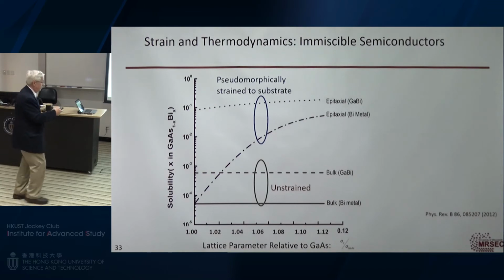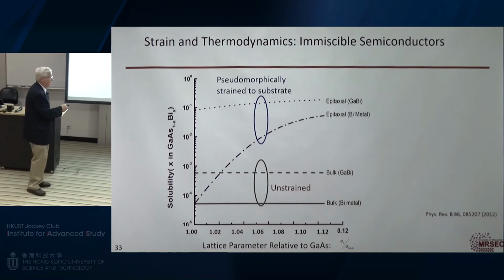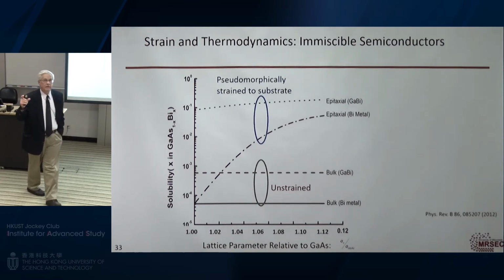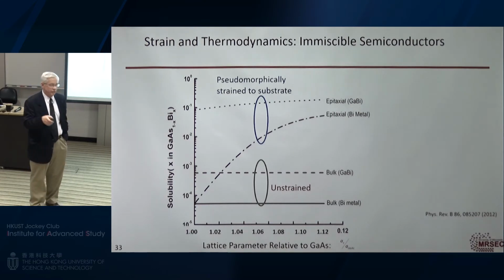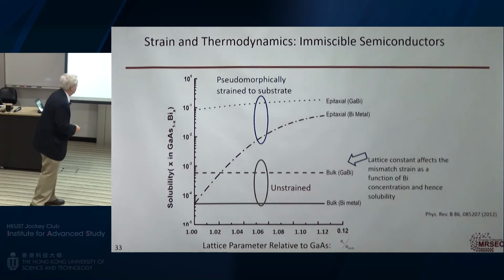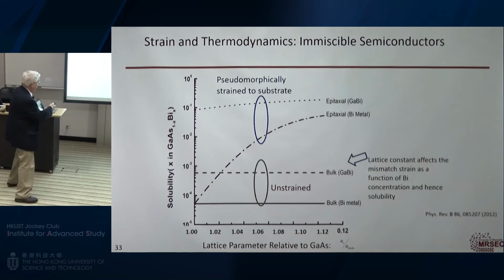The one that I'm interested in is gallium arsenide and bismuth. So bismuth is a big atom. If I put it into gallium arsenide, it actually could be a useful material. But this is the solubility of bismuth in gallium arsenide. And you can see here it's very, very small. It's 1 part in 1,000 or 10,000.